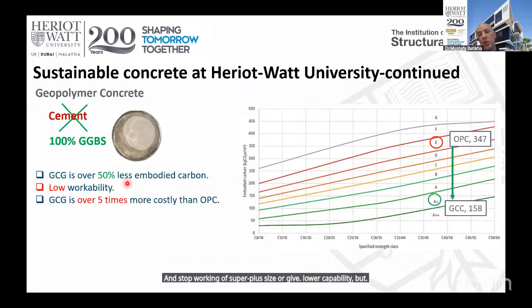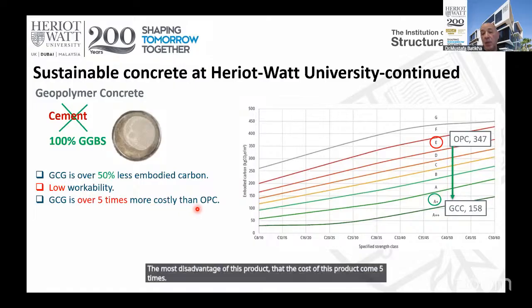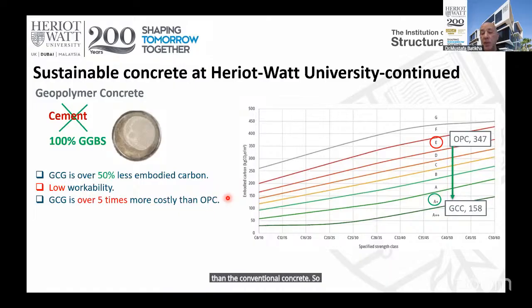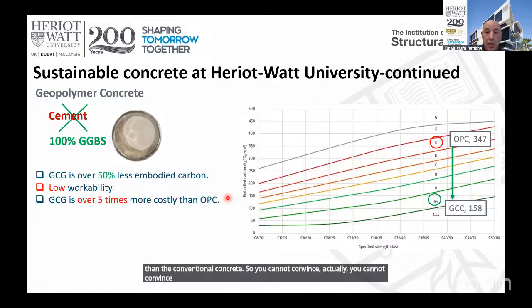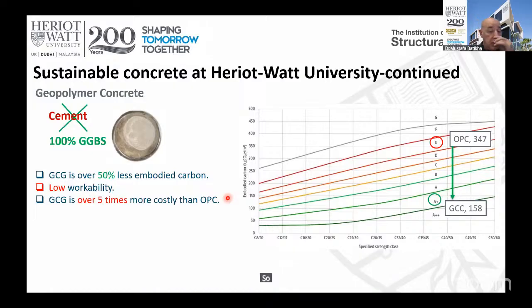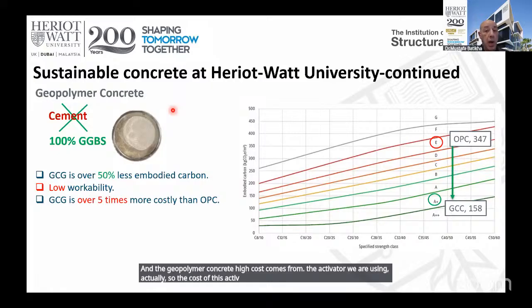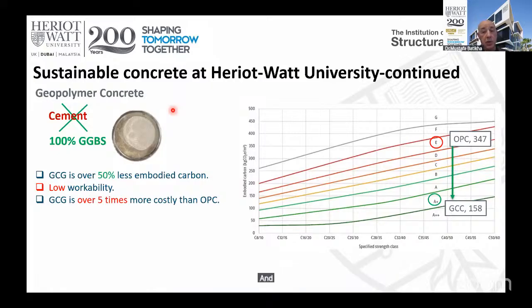But the biggest disadvantage of this product is that the cost comes to 5 times that of conventional concrete. So you cannot convince the market to use this product. So that's the problem. Until we find a geopolymer concrete with low cost, at that time, we can say that we can use the geopolymer concrete. And the high cost of geopolymer concrete comes from the activator we are using. The cost of this activator is too high in the market, and from here, the cost comes.